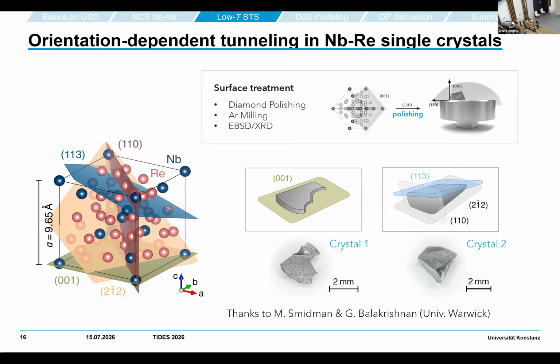When we say central symmetry is broken, with 58 atoms, one might think only one side has symmetry broken, but in fact it is not. There are only the niobium sites on the corner and the one in the center which see a symmetric Wyckoff environment. All the other 56 really have broken symmetry. So symmetry is heavily broken, and I think this is the advantage of this compound.